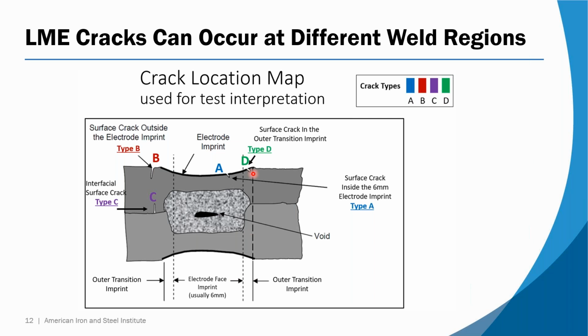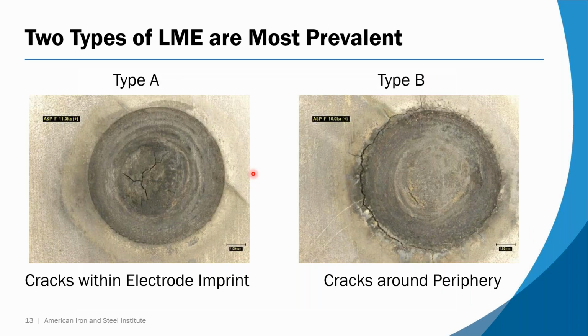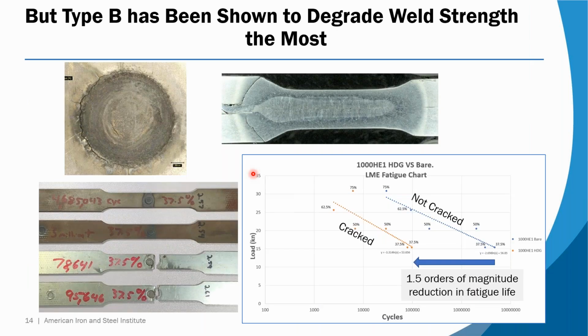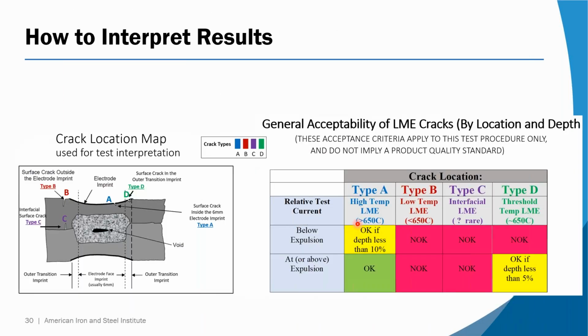Where's the score sheet? There we go—here's your accept/reject criteria for running this test. As far as trying to correlate back to Gleeble results, if you're seeing type A results, that corresponds with the high temperature bubble we saw in the Gleeble results. Type B is the lower temperature stuff, which is what we saw with the third gen steels.